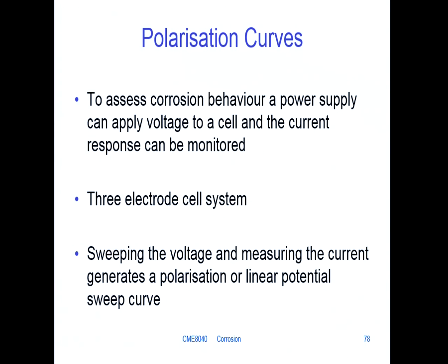So we've got a reference electrode. And then you're going to need to power the system. You're going to want to drive it away from equilibrium. And so you need what they call a counter electrode. And quite often that is something that doesn't contaminate the system. So quite often that's a platinum sheet, so it doesn't corrode away or get attacked.